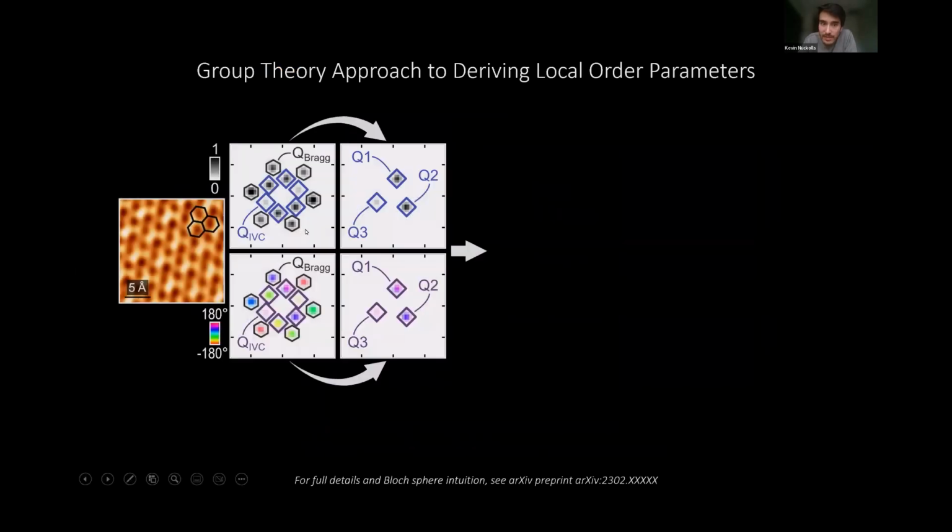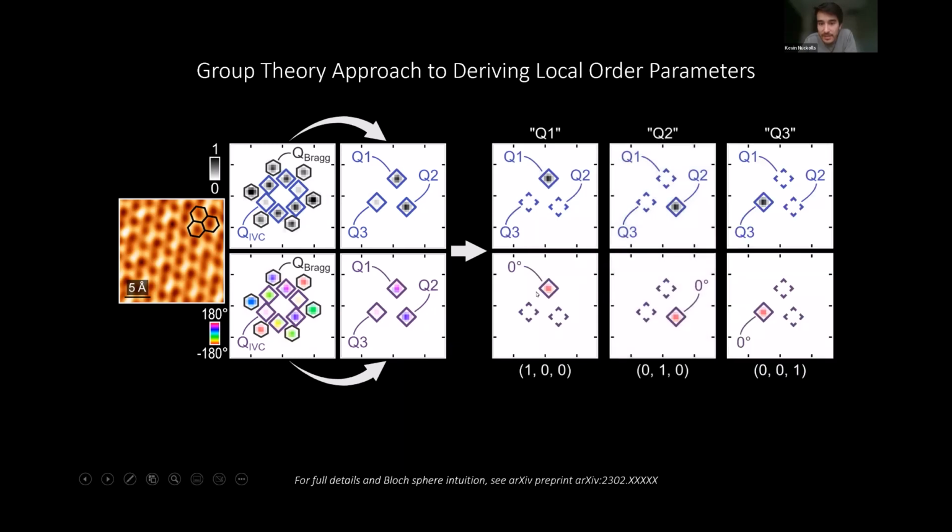To be a bit more precise, the pipeline would look like this: we divide our STM image into a set of small STM topographs, like this 2 by 2 nanometer one. We perform the FFT analysis, project out all of the irrelevant information, and then cast into a new basis, devised such that each basis element only has one of the FFT peaks scaled by a single unit in magnitude and a complex phase of 0.